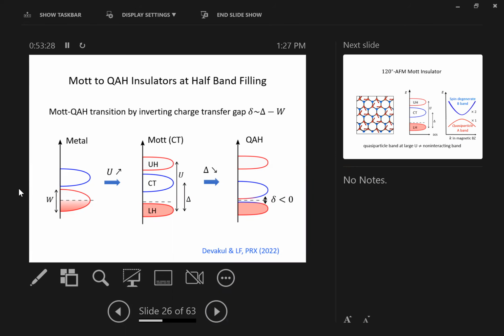So if I dope charge into the system, the doped charge will live in the charge transfer band on the second layer rather than living in a doubly occupied upper Hubbard band. Okay, so this is the starting point of our theory, a charge transfer insulator. And then we can further reduce the charge transfer energy. As we reduce the charge transfer energy, the bottom of the charge transfer band can dip below the top of the lower Hubbard band. And then the hybridization between the 2 bands will create a non-trivial gap.